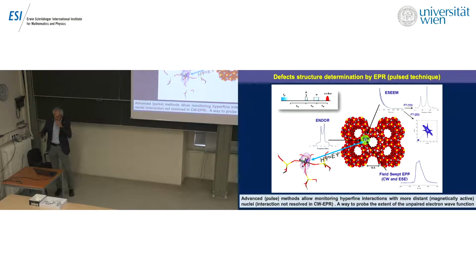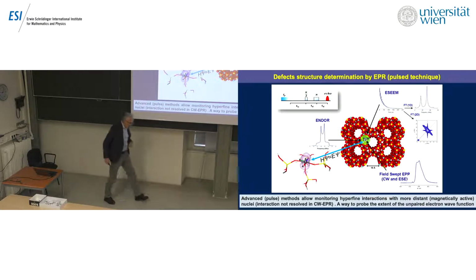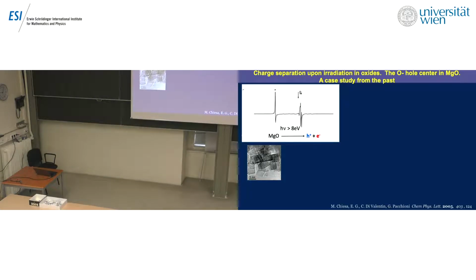Okay, so I want to start with an old case, since here there is a problem that is interesting to this audience: the nature of the wave function associated with the polaron, and the problem of localization and delocalization. There is a case in which we were so lucky to directly measure the localization of a polaron. Magnesium oxide is an insulator, so it's not a semiconducting oxide, with 8 eV of band gap, but if you irradiate with a suitable frequency, you can also in this case separate and create a hole polaron and an electron polaron, or something similar to an electron polaron. I cannot enter into this detail, but here is the signature of the hole polaron, so the hole is stabilized in a particular place of our system.